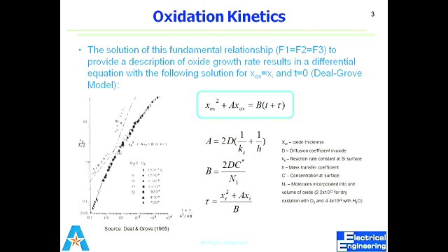If it does not have the initial oxide layer, tau would be equal to 0. And if there is some, let's suppose the initial oxide layer is there, and in order to grow this native oxide it takes maybe 1 millisecond, so I'll have to put tau equal to 1 millisecond. So I'll assume that 1 millisecond has already passed. So tau is actually the time displacement needed to account for the initial oxide layer.